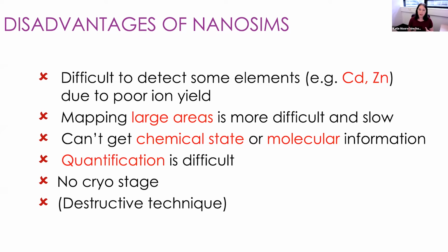But I put it in brackets because actually this can also be advantageous for us. Because we're removing material layer by layer, what we can actually do is see how distributions change as you go down in depth. So you can make a depth profile through your sample, or if you're imaging, you can create a 3D reconstruction of your sample to see how elemental distribution changes with depth.